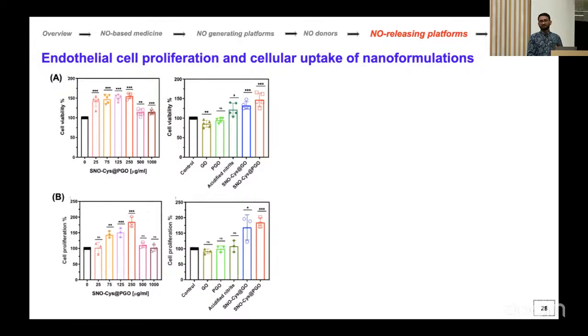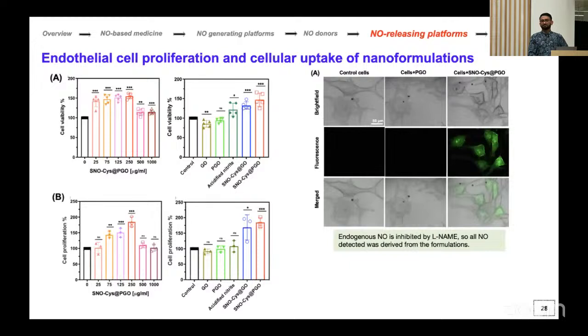Okay, so we see from the readout that endothelial cells are proliferating. Why? So then we use a nitric oxide sensitive fluorescent dye called DAF to show whether nitric oxide is inside these endothelial cells or not. And we show that it is. Because endothelial cells also produce nitric oxide, we also use a nitric oxide inhibitor called L-NAME to stop the production of nitric oxide from these endothelial cells, just to confirm that these effects are arising from our formulation. Okay, so nitric oxide is inside the cell.